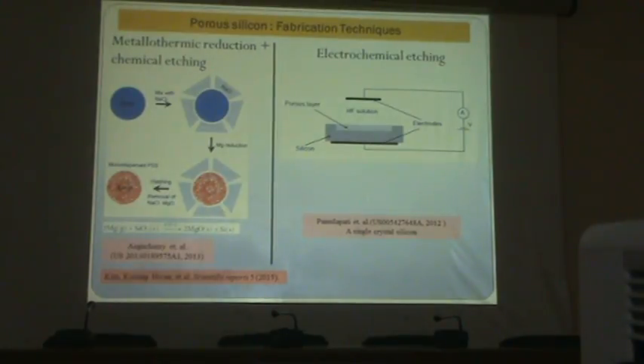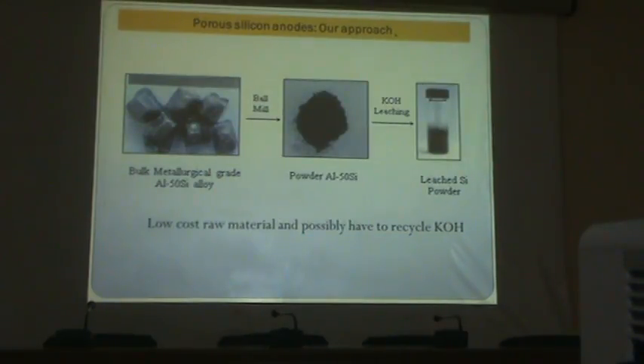We looked around at how they do it. Everything is pretty complicated: electrochemical etching, metallothermic reduction, chemical etching, a lot of very cumbersome, long processes. Then we thought, what's a better way to do it? We had some knowledge from earlier about aluminum silicon alloys. How can we etch out aluminum? We knew very well that aluminum reacts vigorously with potassium hydroxide.